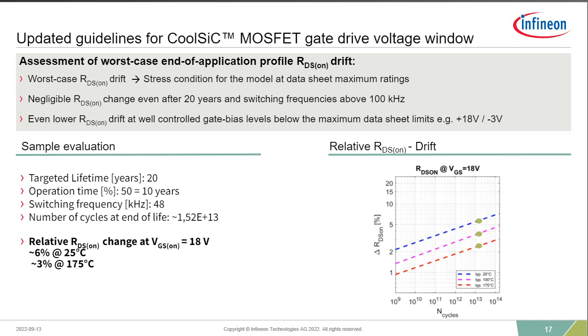This will allow you to also select a higher RDS(on) specification in the devices, which means a lower price for you and still have the long-term stability of the device with respect to RDS(on) in your application. So let's say that you needed 40 milliohms in your application in order to keep the losses at an attractive level for you, you could choose a 35 milliohm device instead of choosing a competitive 30 milliohm device, and basically stay within the RDS(on) specification over the lifetime of your application. So ensuring that devices do not wear and go outside the specification and cause thermal issues in your application.